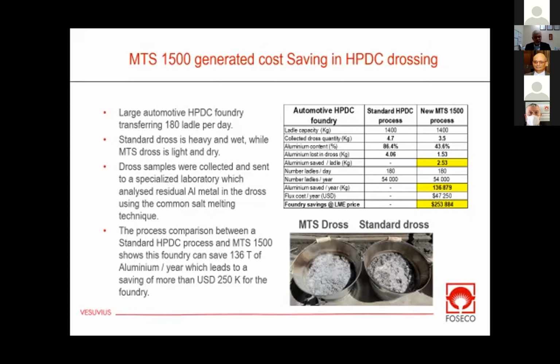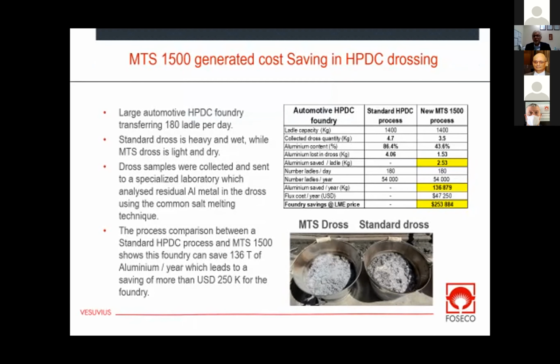The processing time is 3 minutes. The temperature of the melt is the same. So all we did is, rather than use their standard HPDC process, we took the ladle and we used our standard MTS process. And the result of that is a saving of 136 tons, which when I calculate at LME prices is more than $250,000 per year of saving.